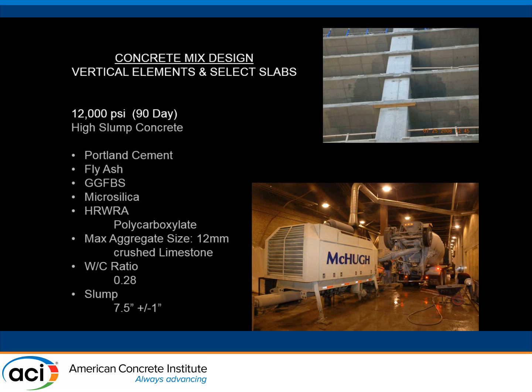It wasn't a self-consolidating mix, but it was certainly a high slump concrete, high flow. So you can see we've got the high range water reducing admixture. In this case, we don't have a viscosity modifier because the flow wasn't nearly as high as the outrigger zones where we had self-consolidating. So it wasn't as necessary to do that to maintain the stability.